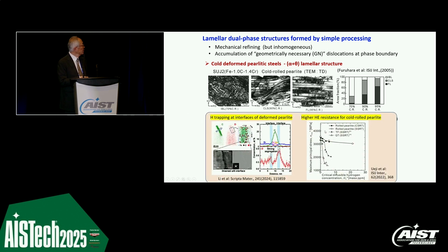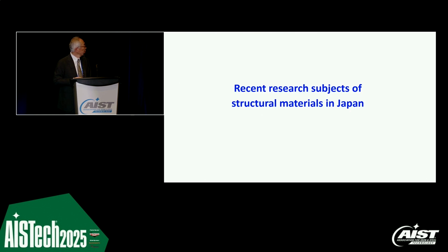For this lamellar cold rolled pearlite case, recently in Japan, a research group found hydrogen can be trapped at the cementite-ferrite lamella interface, and actually, better suppression of hydrogen enrichment. So this may be a very interesting research area in hydrogen enrichment suppression. Okay.